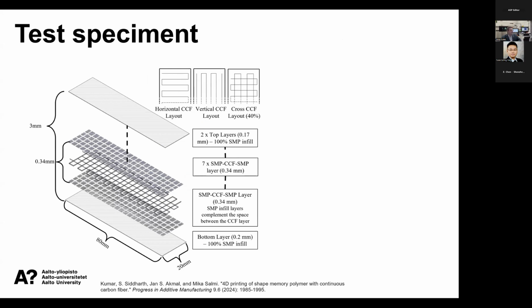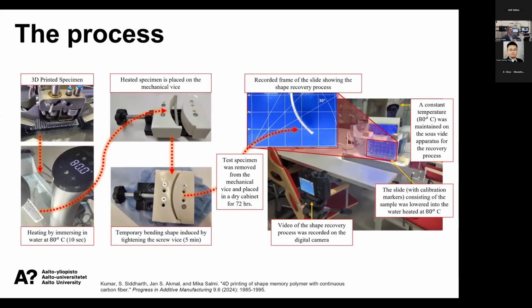First we make a bottom layer, which is pure shape memory polymer. Then we have layers with carbon fibers and shape memory polymer, and then the top layers, which are again pure shape memory polymer, and between the fiber layers there is also shape memory polymer, so we get nice matrix parts. Then the process: we test the specimens, heat them up at 80 degrees Celsius for 10 seconds, and then mechanically we want to change the shape.